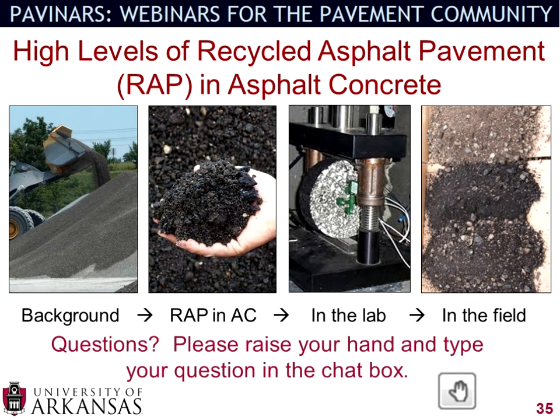Going down the list here, again, thank you to Eric for clearing up Shannon's question. You assume that the asphalt cement that's extracted from the RAP is virgin, and then you put it through the RTFO and the PAV aging like you would any normal binder. And Shannon added on, yes, the asphalt cement from the RAP is aged, but at least in Ohio, they continue putting it through the aging procedure because that is what's going to happen to it in the future in the field anyway. So they want to make sure that the mix they're evaluating goes through the aging in the lab that's going to happen then in the field.